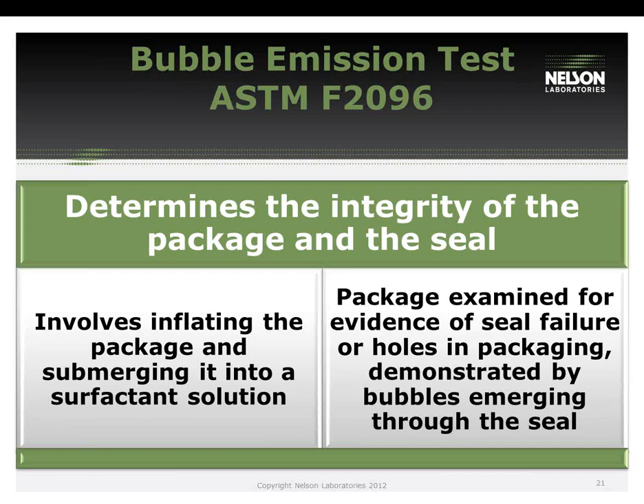Also, if you do this test on Tyvek materials and you notice that there is a slow leak or a slow amount of bubbles coming from the seal area, it's always a good idea to follow up Tyvek tests with the dye migration test. Tyvek sometimes has the capability of delaminating inside the material, but that doesn't affect the integrity of the package. So by following up a bubble emission failure of slow leaks with a dye migration test, you can confirm that it is a true failure rather than just the Tyvek delaminating.